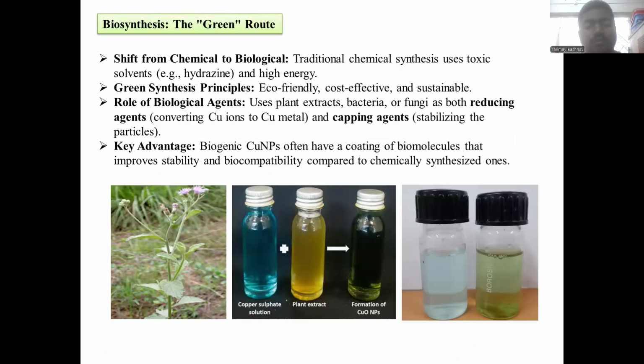So first of all, our approach is the green synthesis of that copper nanoparticles, because the chemical synthesis method produces various toxic byproducts. So we chose a green synthesis route for this study. Unlike chemical methods that use toxic reducing agents, we utilize plant extract. So this approach is not only eco-friendly and cost effective, but also uses natural biomolecules and the capping agents to stabilize the copper nanoparticles. Our goal was to find a local plant species that could efficiently reduce copper ions to metallic nanoparticles without hazardous byproducts.